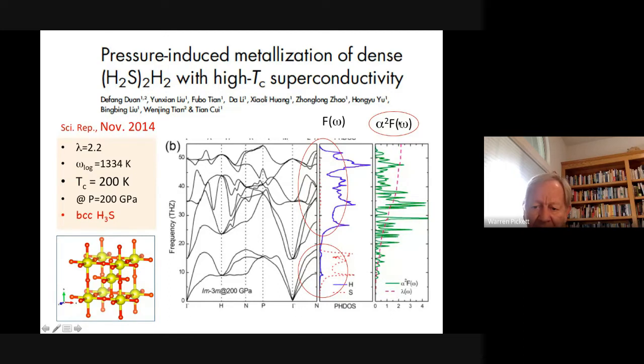Now here's alpha squared F, but this is a low resolution calculation of it, because it should look a lot like F of omega in structure. It should just be weighted by alpha squared. So some parts may be decreased and some parts increased and so forth. But this integral over these, you see, this is just a series of broadened delta functions, many delta functions they calculated. And they got lambda 2.2, and other people doing this more converged to get very similar value and a very similar value of TC. This is correct.